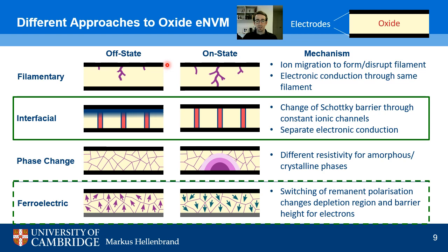So if this filament is disrupted and not complete from one electrode to the other, the current flowing through the device will be low, and we can identify this as a state 0. Whereas if the filament is formed, we get a higher current, so we can identify this as a state 1. The challenge with this approach is that the formation of these filaments is rather random, because while we can break bonds between the atoms and thus make oxygen vacancies move around, we cannot control exactly which of the bonds are broken and along which paths the oxygen vacancies move.